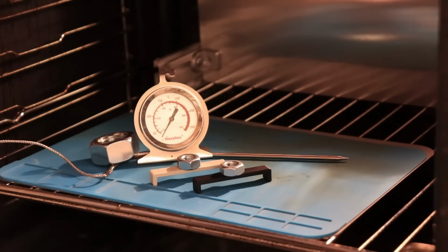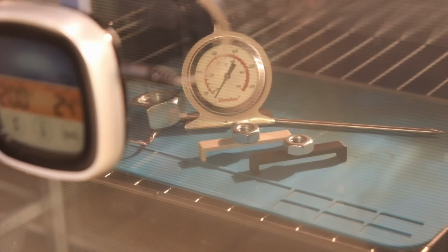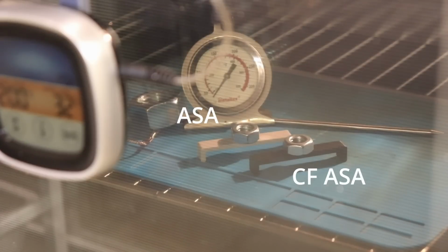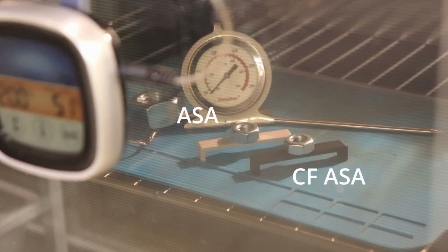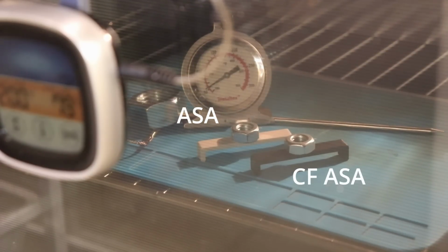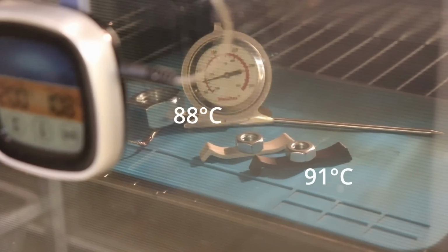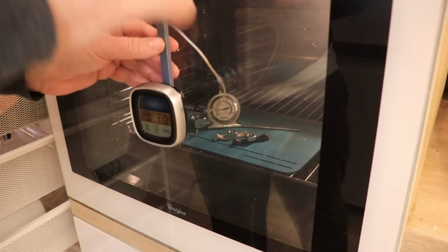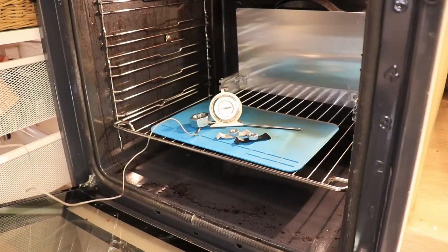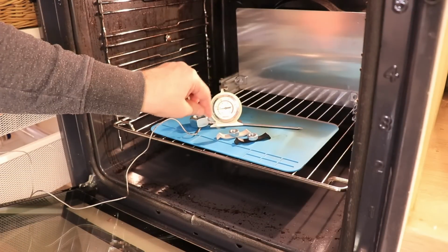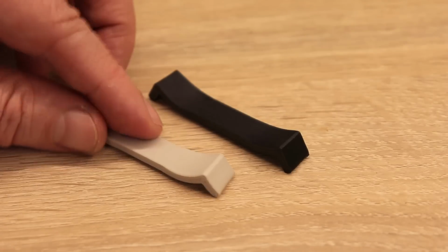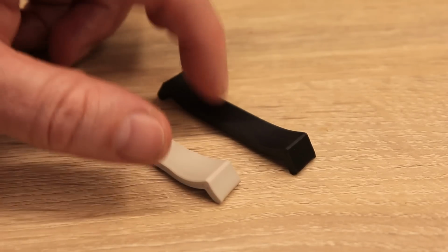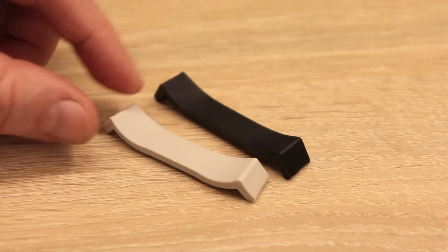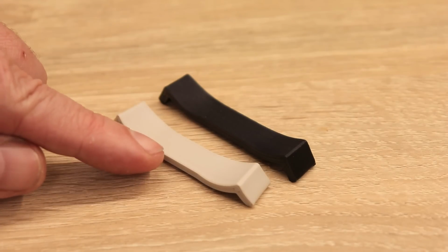And now my oven test, when I want to record the temperature of the first deformation. The main measuring unit is the cooking thermometer. You can see its screen on the left side. The one inside the oven is accurate too, but with a small delay. And as expected, ASA started with deformation around 90 degrees Celsius. Okay, I can stop the experiment now. I will analyze the footage later, but for the feeling they are very similar now after maybe 2 minutes. But a little bit more deformation on regular ASA.